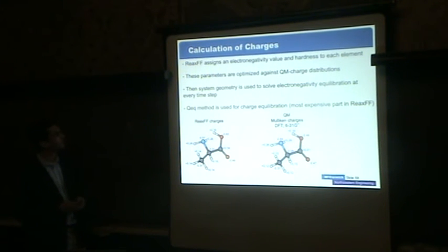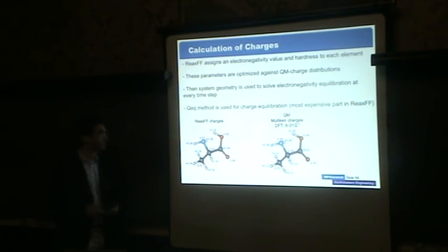It can make a difference in your interaction energies and other calculations. So there's a method called the QEq method that is used in reactive force fields to calculate charges at every time step. Of course, this is why it's a lot more time-consuming to do reactive simulation: you have to know the charges at every step and recalculate them using sophisticated methods.